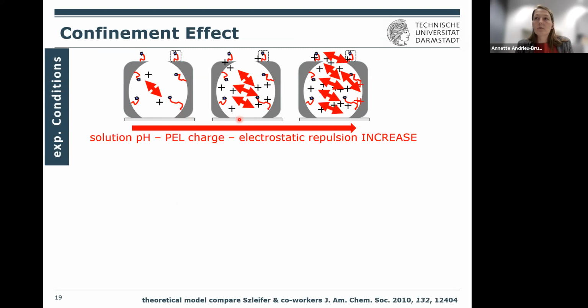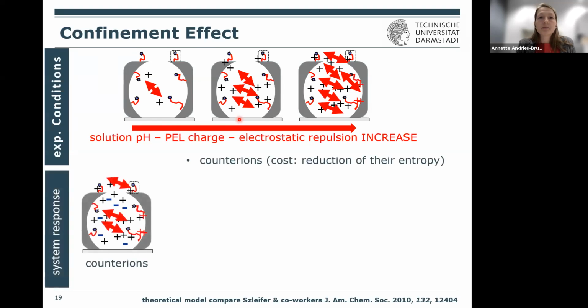And in contrast to a polymer solution, these charges cannot just increase their distance as they would like to do if they would have space. So the question is, how can this be equilibrated? And then there are 3 possibilities. You can, of course, include counter ions. This is at the cost of reduction of their entropy.